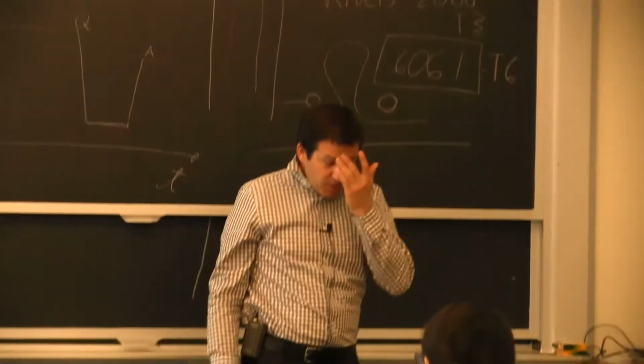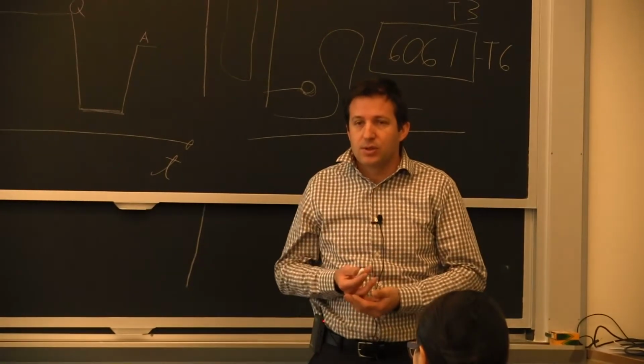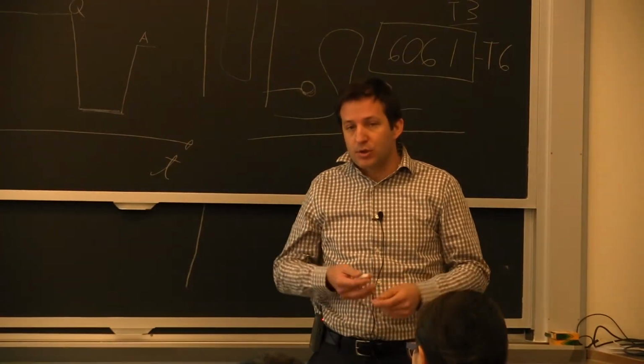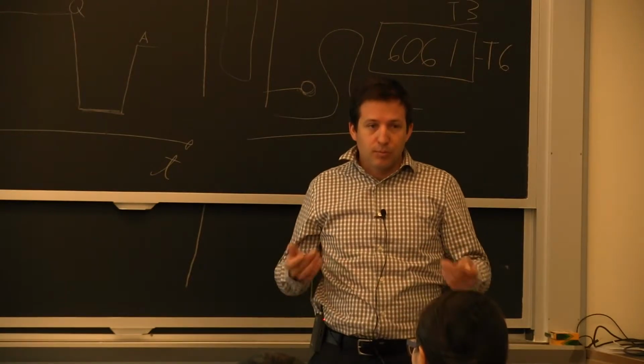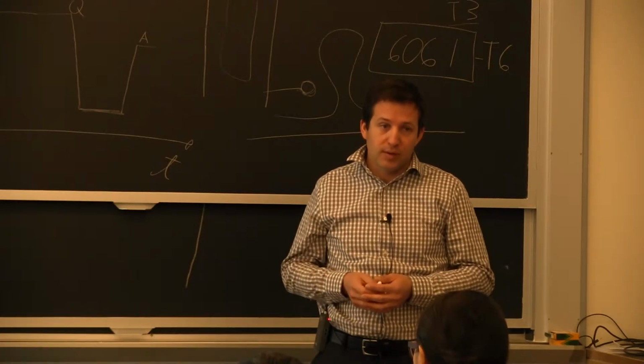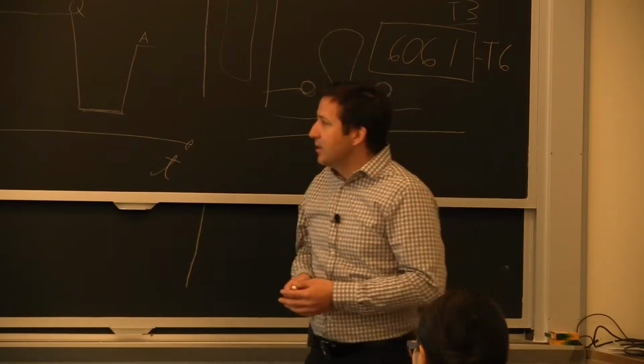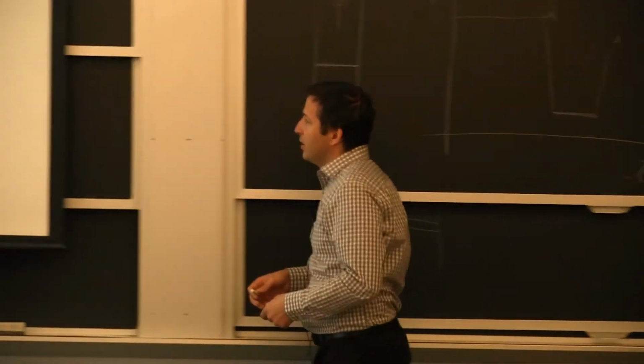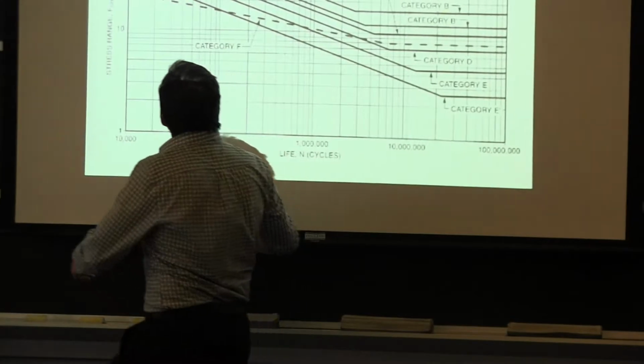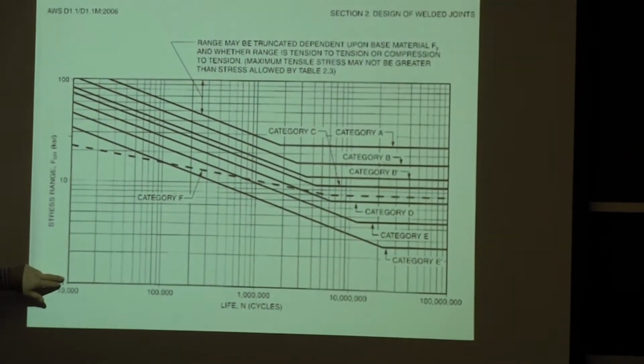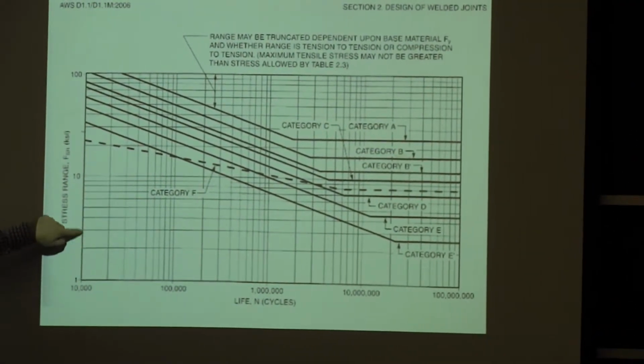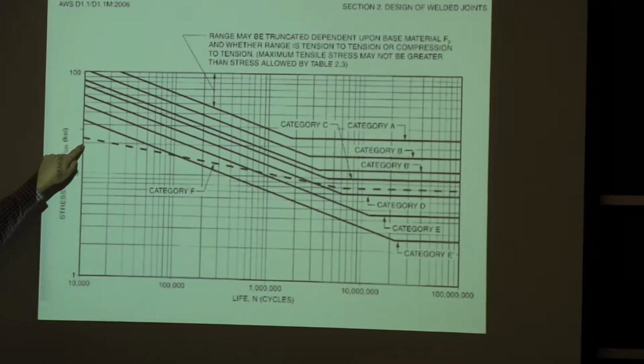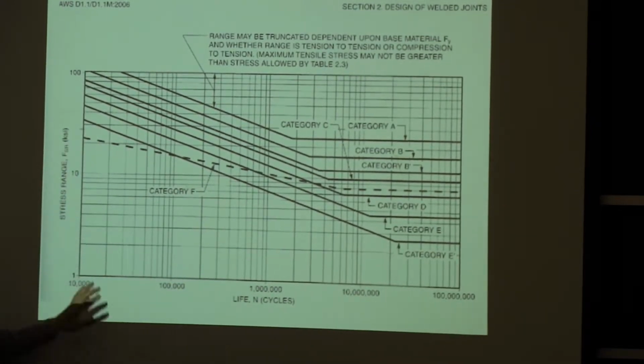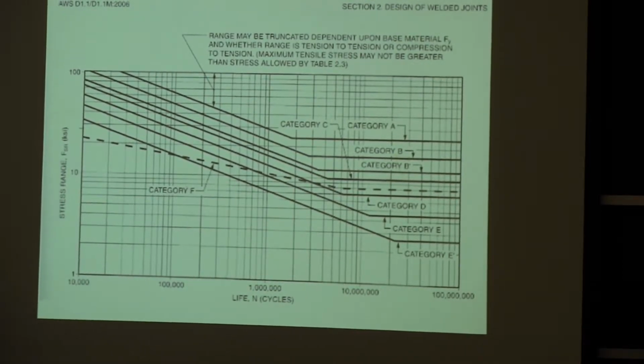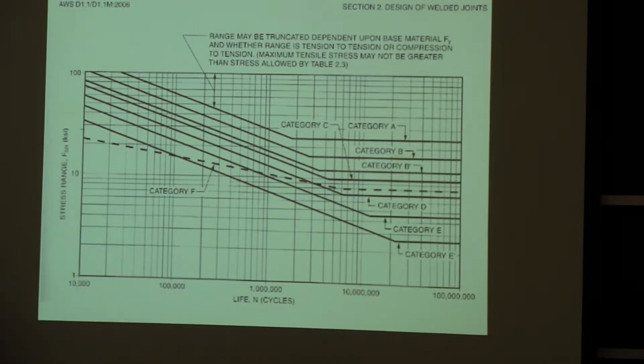And the main reason is all the residual stresses, the change in microstructure, the heat affected zone, will form cracks in conditions where you wouldn't have cracks otherwise. This knockdown factor of 5, as you can see, if I only assume I have a factor of 10 here, 10,000 cycles, is much less. At 10,000 cycles, it will still be allowed, according to this framework of AWS, to have a stress range of 20 KSI. It's really when you take it to a longer life.